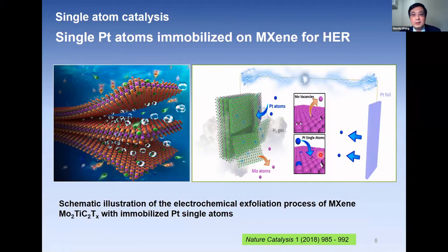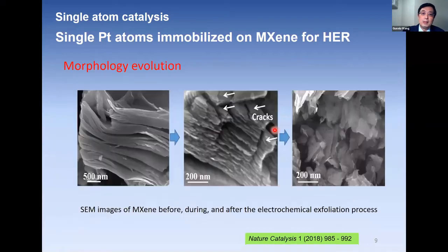So this is the electrochemical cell. We just put each MAX phase as one electrode and put platinum as the counter electrode. When you apply the voltage sweep, the MAX phase is delaminated and becomes MXene nanosheets. Simultaneously, platinum atoms dissolve in the electrolyte and migrate to the surface of the MXene phase and finally deposit on the surface of the MXene phase.